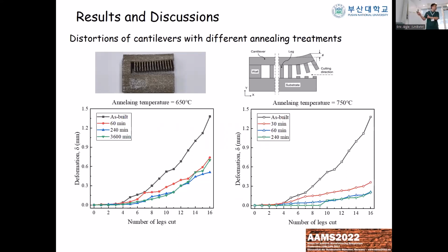So you can see the distortion while cutting the legs, and here in the graph we have the number of legs cut on the x-axis, and on the y-axis is the deformation. So we are basically cutting the legs and measuring the deformation of this part upward, and then we plot here. As we can see, when the annealing temperature was 650 degrees C, then as in the as-built state, we have a large amount of distortion.